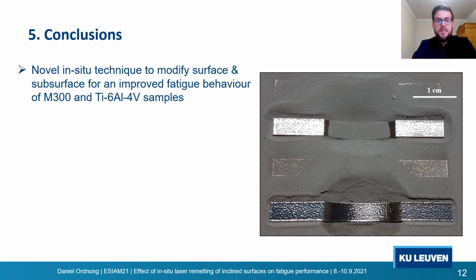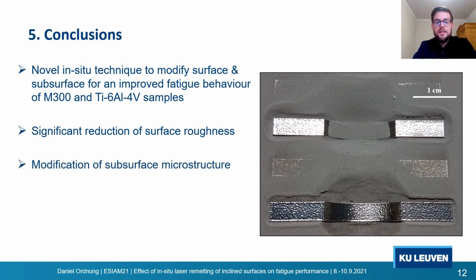In situ laser remelting of inclined surfaces appears to impact different factors in a beneficial way for fatigue performance. On the one hand, the laser remelting leads to a significant reduction of the surface roughness, for maraging steel of about 47% and for titanium alloy of about 43%. On the other hand, the laser remelting process modifies the subsurface microstructure. Here we could see a remelted layer of about 50 micrometer thickness, which appears to have a beneficial impact on the fatigue behavior.